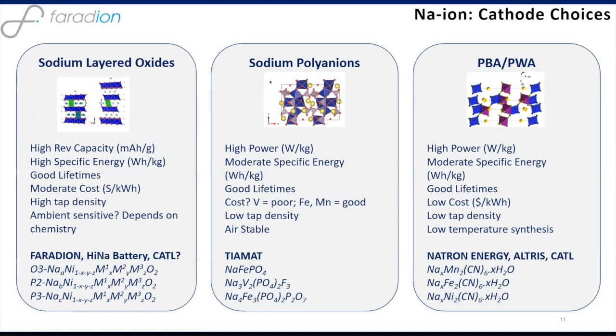So really, if you're looking at entering the energy market for sodium ion batteries, you're pretty well confined to using one of the sodium layered oxides. And of the companies that are trying to commercialize sodium layered oxides, we include obviously Faradion, Hina Battery in China. And now we hear that probably CATL will also be looking at developing a layered oxide chemistry as well. If you make these materials correctly with the right substitutions and the right physical properties, then you can end up with materials with relatively high density, high specific energy, and very good lifetimes. The high density means you can formulate electrodes with high areal capacity, which are then suitable for energy applications.